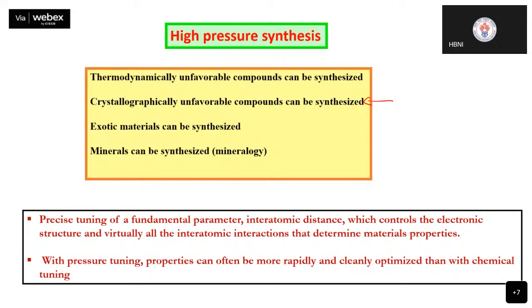For example, in case of silicate, silicon cannot have a coordination number greater than 4. But under high pressure synthesis, a polymorph called stishovite has been synthesized, which has silicon in the coordination number of 6, because you compressed it. You literally ordered it to do so. Okay. So crystallographically unfavorable compounds are formed, thermodynamically unfavorable compounds are formed. And if you're tampering with the basic qualities, you can actually get exotic material, and synthesis of minerals is possible by using high pressure synthesis.